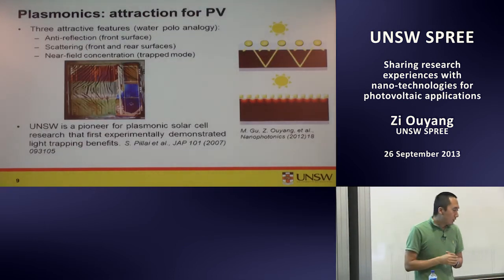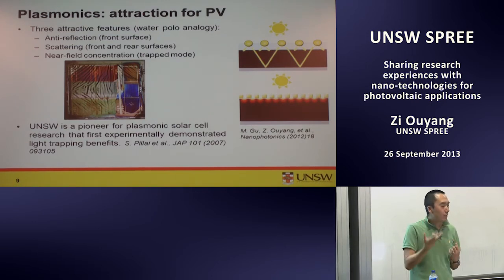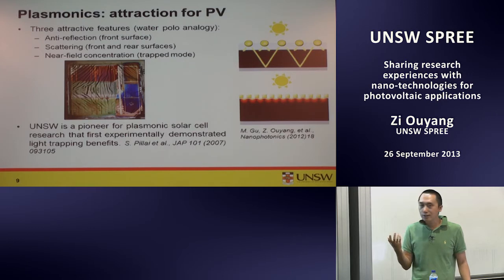So why are plasmonics so attractive for photovoltaics? If we think back to the water polo thing, you have an anti-reflection effect because the energy always goes to the high refractive index material, which is the silicon for our research. And it has a scattering effect because when the nanoparticles re-radiate, the electrons re-radiate the energy, it won't go straight underneath. It will go everywhere. That's a scattering effect. That's what we like, because we improve the path of the light.